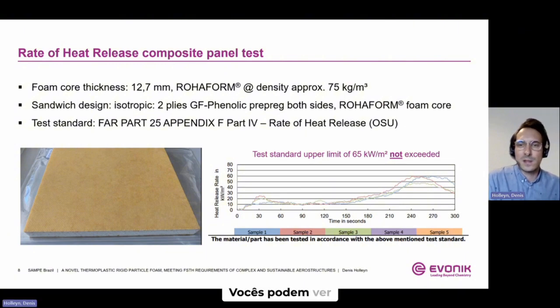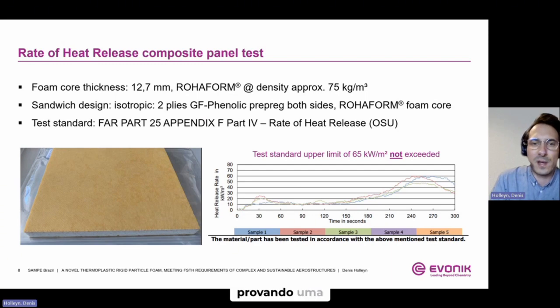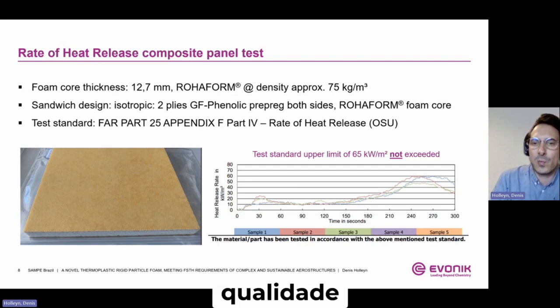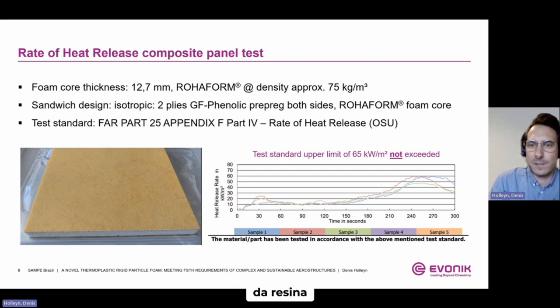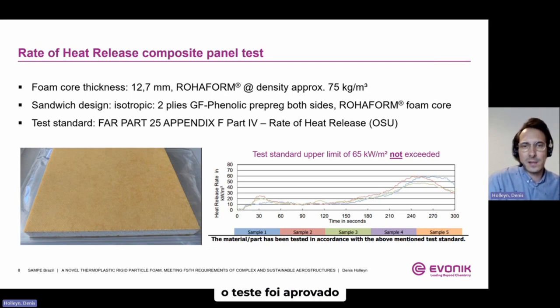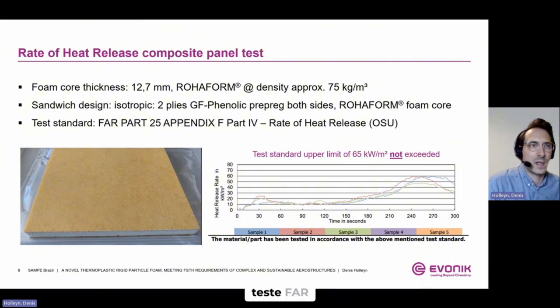You can see the sandwich panel on the left-hand side of this slide, providing an excellent surface quality with a low porosity of the resin. If we look at the test result diagram on the right-hand side of this slide, we can see that the limit of 65 kilowatts per square meter was not exceeded by each of the 5 test specimens. Thus, the test was passed according to the applicable limits by the FAR test standard.